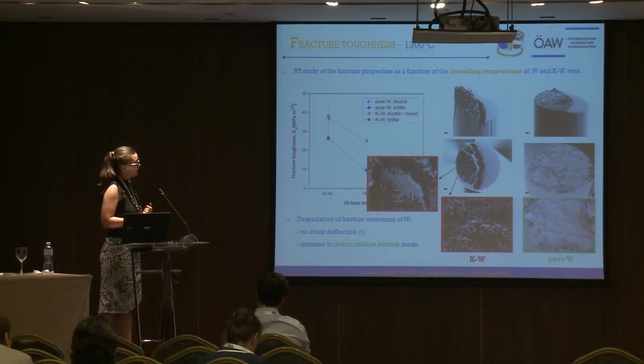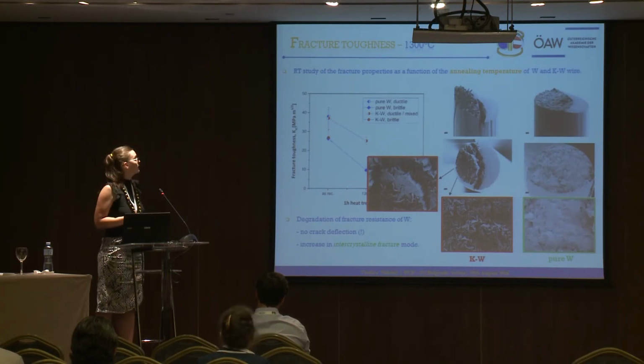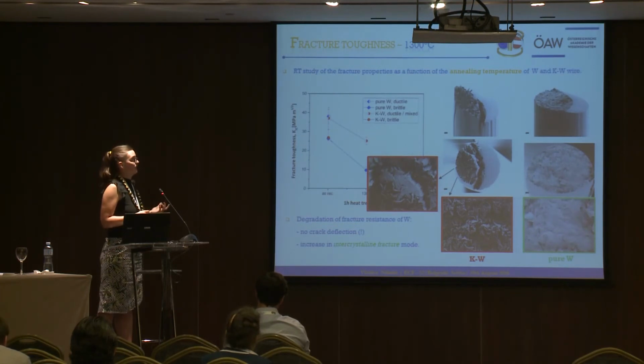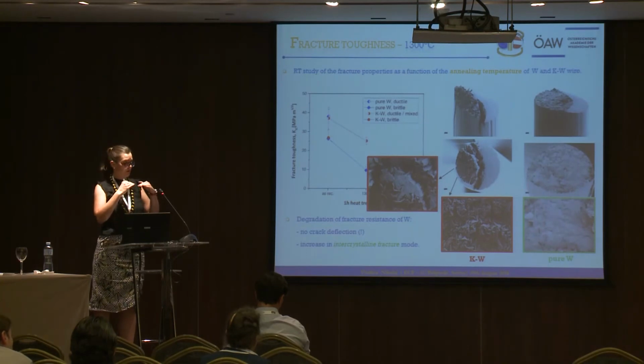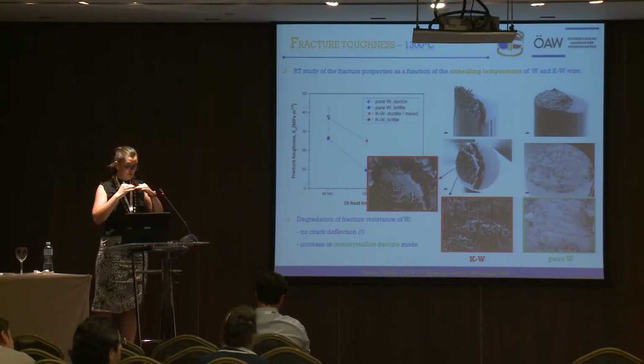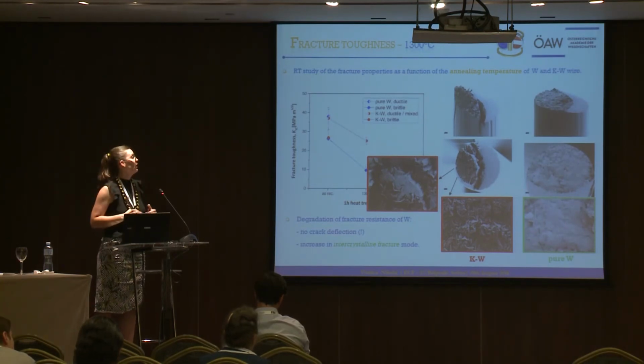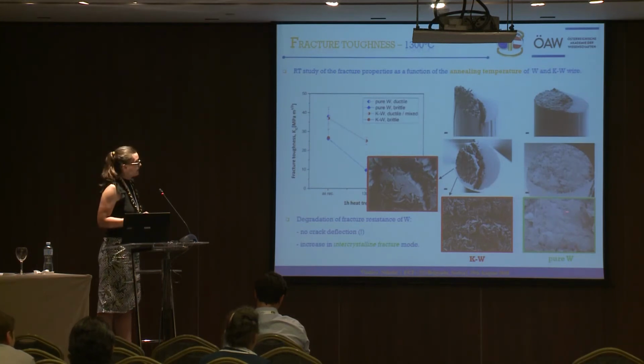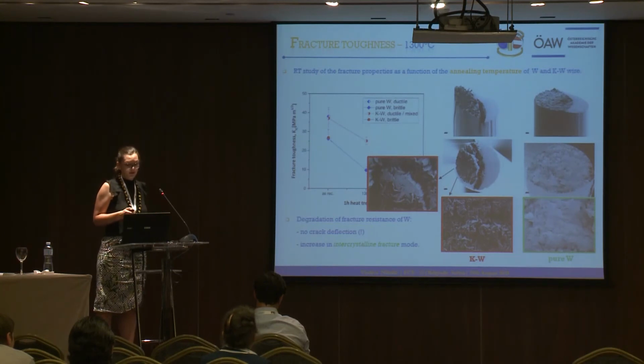And now if you look at the pure tungsten, we see a completely different picture after annealing. So here there is no crack deflection at all. So our initial direction of the crack propagation is preserved. So it just goes through our wire. And in this case we have transcrystalline cleavage again, but there are also some intercrystalline areas as well.